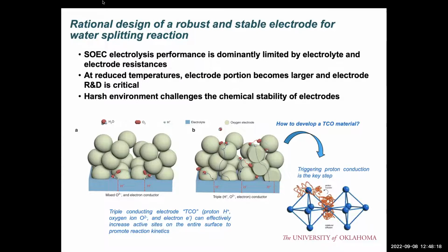So in order to facilitate the fast hydrogen production rate, the conductivity of the electrode material is very important. Normally, right now, the perovskite electrode is a mixed ionic, oxygen ion and electron conductor, which is a two-phase conductor. This can limit the reaction on the surface of the electrode, limited to the triple phase boundary.